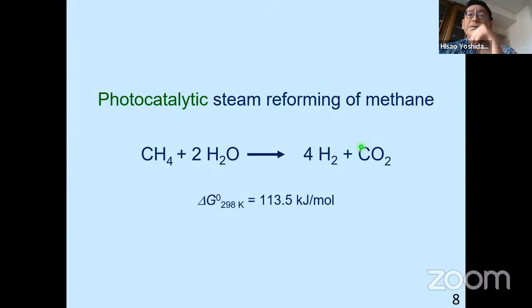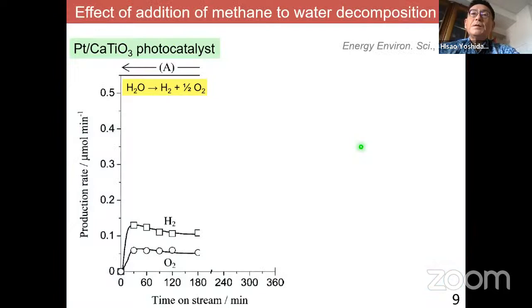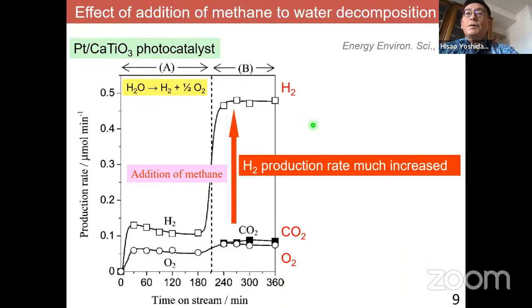First, photocatalytic reaction, photocatalytic steam reforming of methane. Here, I demonstrate the water splitting by using calcium titanate with platinum co-catalyst. In this case, we flow the water vapor into the photocatalyst, and we can confirm hydrogen and oxygen as products. It's also a very clever method to get the hydrogen. But if we add the methane into the system, the efficiency jumped up to produce hydrogen and CO2.